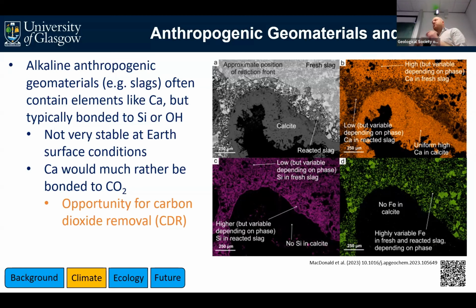And that might sound like a bad thing, but actually it presents an interesting opportunity for us in a climate context, because the calcium in those slags, for example, would much rather be bonded to the carbon dioxide molecule than to the silicon, the oxygen, the hydrogen in the slag when it's first cooled and crystallized. And because of that favorable reaction at Earth's surface conditions with carbon dioxide, it presents an opportunity for mineralizing and therefore removing CO2 gas, either from a waste stream, from maybe a power station or some other industrial processes, or directly from the atmosphere, CO2 that's already in the atmosphere. And so some work that I've done in recent years has looked very closely to try and understand that CO2 mineralization process.